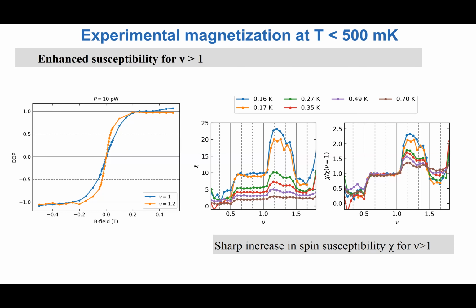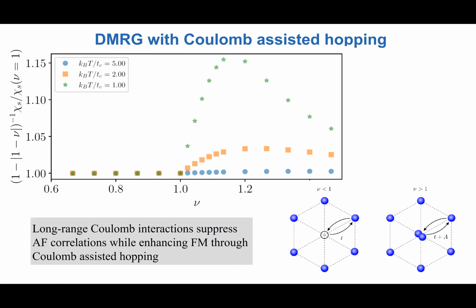You see that below nu equals one, it's a paramagnetic response, and then there's an abrupt jump in spin susceptibility, indicating that we're dealing with the Nagaoka kinetic magnets. Okay, so I will just skip this.